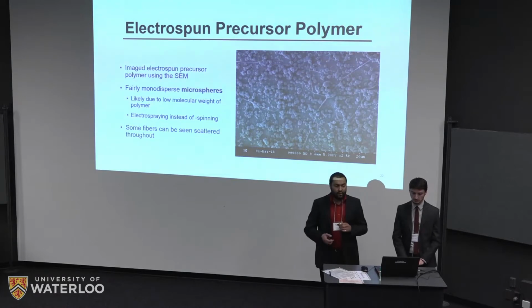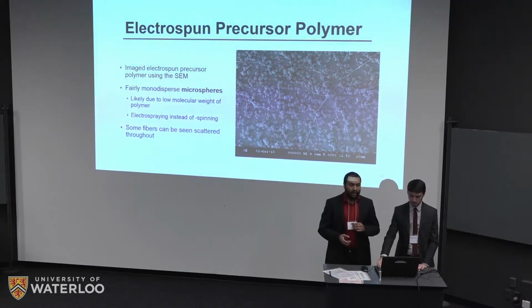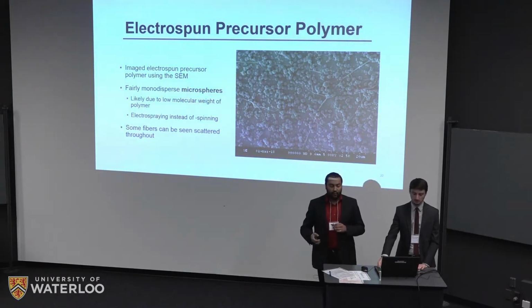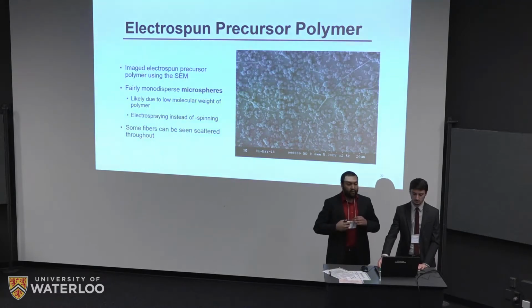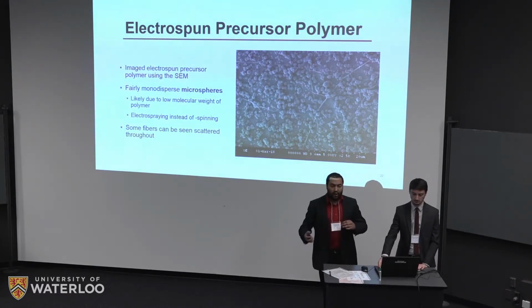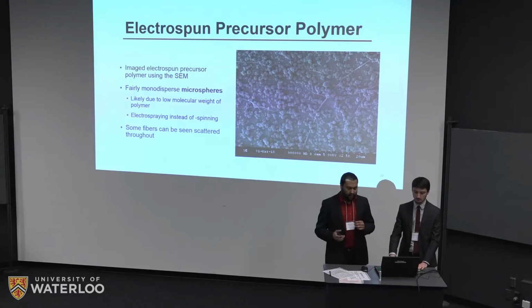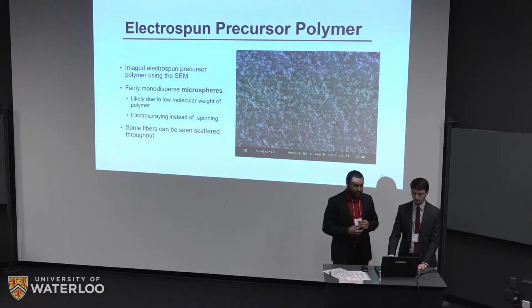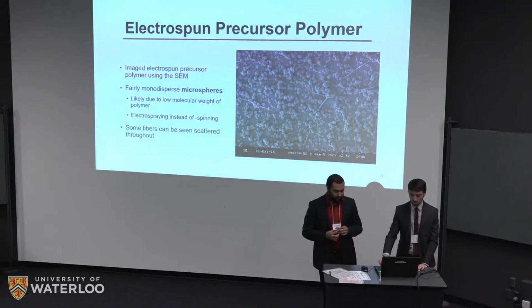This is most likely due to the molecular weight of the polyamic acid that we made. We're hypothesizing that because we made it ourselves, the molecular weight wasn't large enough to keep the stream cohesive. So we got microspheres instead.